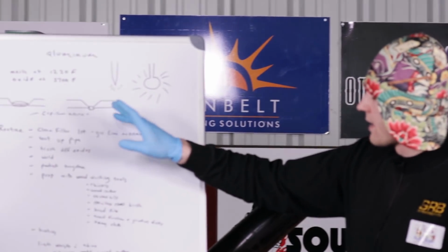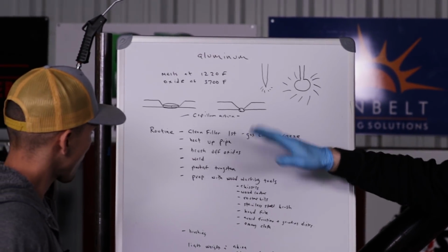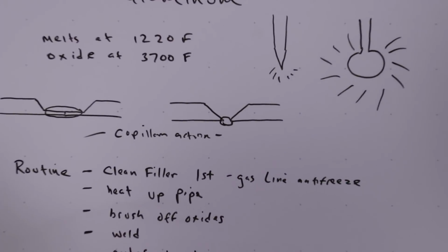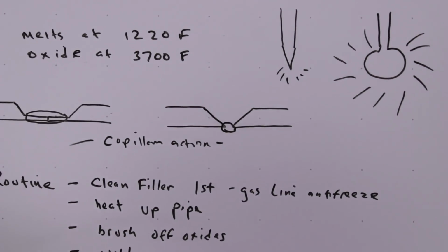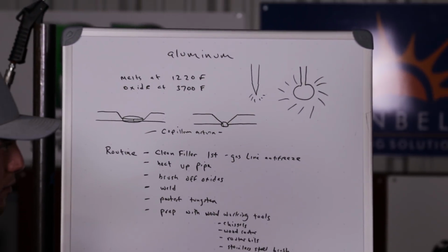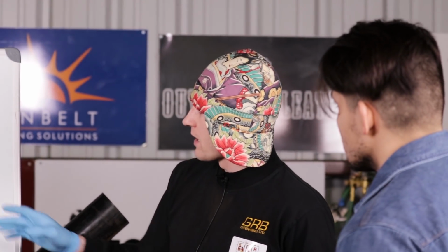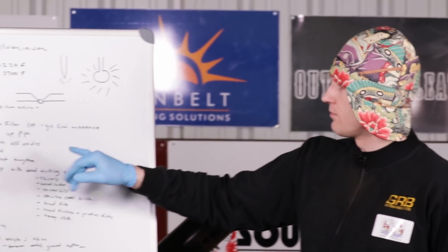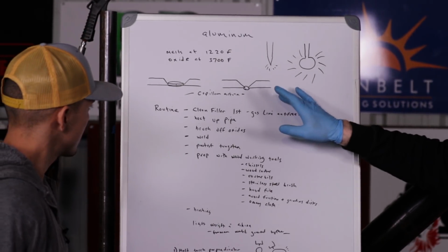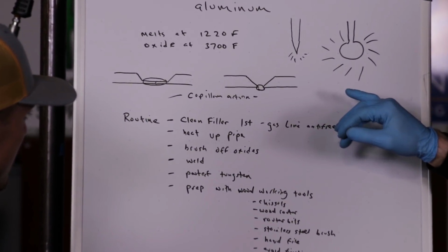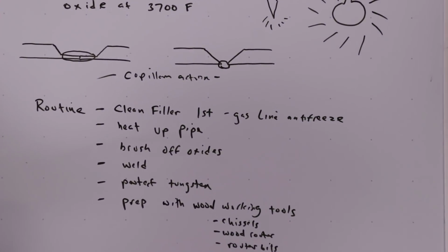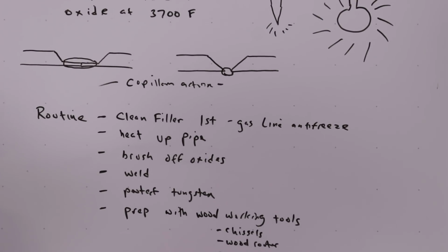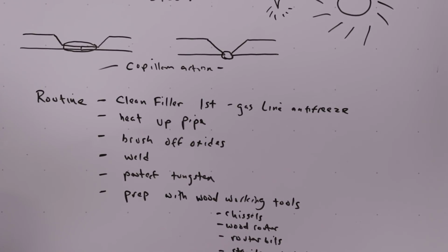Also, the butt weld will be a normal, typical butt weld. I'll be using a 1/8 gap in the video and a 1/8 filler metal, and I'll have the filler metal on the outside of the pipe. So I'll be dabbing in on the outside of the pipe there, and the root pass will be going in via capillary action, but that particular pipe will be purged. Also in the video, I'll be using a 2% lanthanated tungsten with a sharp point, so the arc is a lot more focused when I do the root pass.